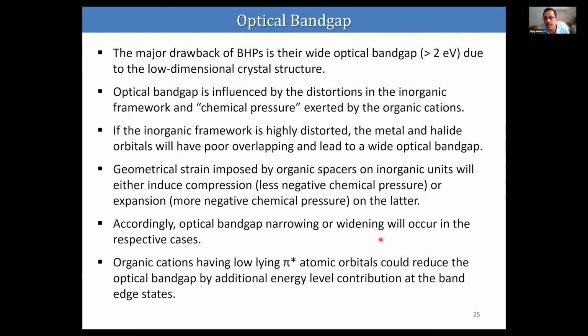And the other one is the chemical pressure exerted by the organic cation. So if you use a bigger organic cation, it can exert chemical pressure. It can be negative or positive, either compression, and that normally gives a narrowing of the band gap. And in the case of expansion, that will lead to a widening of the band gap. So what we observed is that organic cations having low-lying pi star atomic orbitals could reduce the optical band gap by additional energy level contribution at the band edge states.